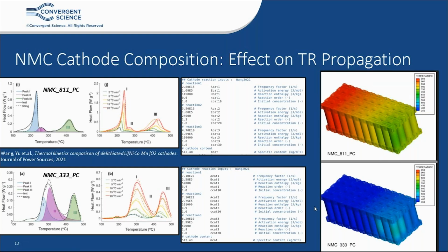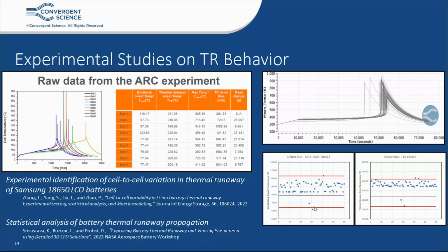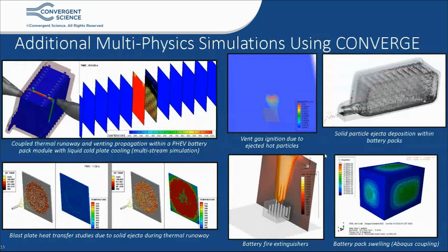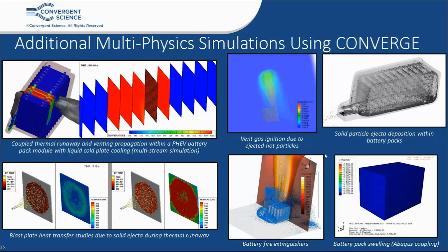Something we also want to keep in mind is that thermal runaway behavior is a chaotic behavior, and we want to treat it as a statistical problem. Researchers at University of Tennessee have showcased that for the same battery, the same chemistry, and repeated tests, you get very different thermal runaway behavior. So this is something to keep in mind. We want to do more experimental tests to give us a full understanding of the statistical nature of the thermal runaway problem. We have run statistical simulations for battery thermal runaway propagation and presented it at the NASA battery workshop. We have taken multiple experimental data for the same battery, converted them to statistically significant thermal runaway reaction parameters, and then explored a wide design set for your thermal runaway propagation problem. And now once you have a full understanding of a thermal runaway process and a well-calibrated mechanism, you can move ahead and include more physics into your simulation involving vent gas ejection, vent gas combustion, solid particle ejection, and so forth.